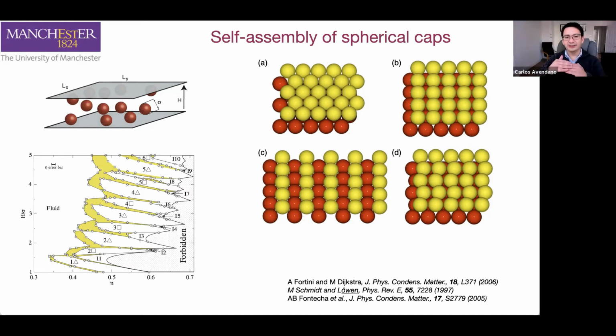But as soon as you start increasing the distance between the two plates, the two walls, well, particles will start adopting different types of positions. And with that, they can form monolayers, bilayers, 3 layers. And typically they alternate between having something like a square symmetry with something that has triangular or hexagonal symmetry. So at least we have a reference system, which is the spheres, to try to compare what happens with the non-spherical particles that we want to study.